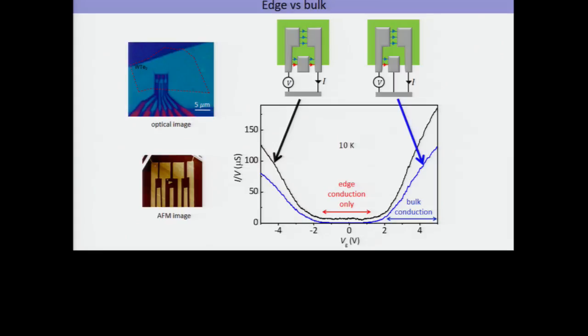And you see that when you do that, you get this blue trace, and this plateau is gone. But there's still conduction. There's still bulk conduction. This rise of the conductivity at high and low doping still occurs. So the bulk conduction is switching on in that region as you go to high N or P doping. But the edge state, we've shorted it out.